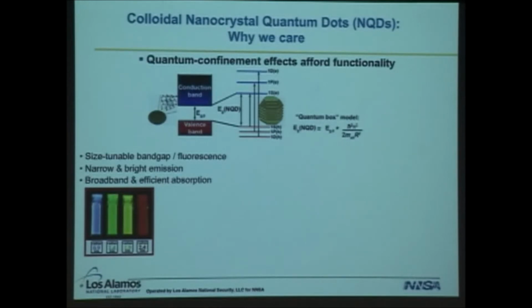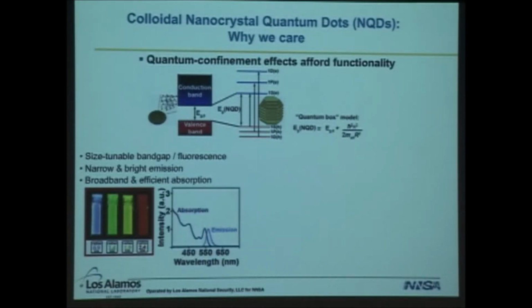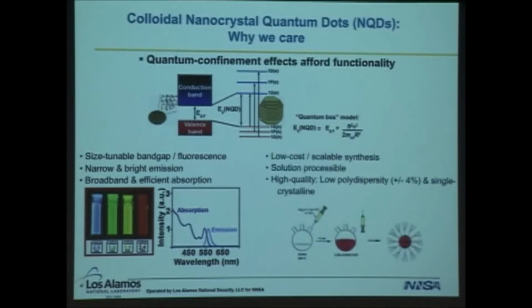And in addition, and this is significant, the emission that we achieve is narrow band and highly efficient. In these best case scenarios, quantum yields are approaching 100%, approaching unity, so 1 photon in, 1 photon out. And in addition, the absorption spectra are quasi-broadband, which allows us to optically excite quantum dots very, very easily with a multitude of energies. And so they're very useful in that sense. And also the solution phase synthesis that's used is low cost, it's scalable, the particles are solution processable using polymers, sol gels, and so forth.